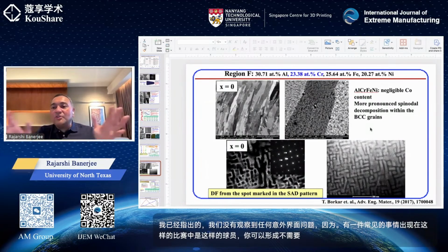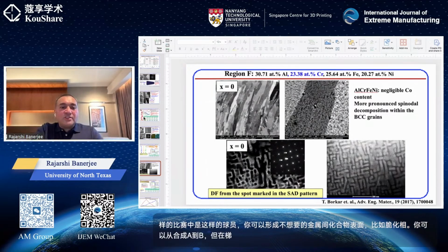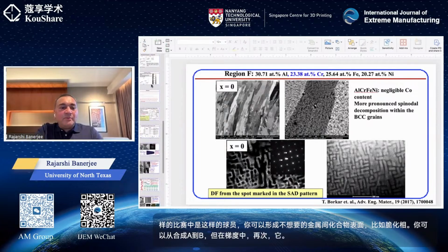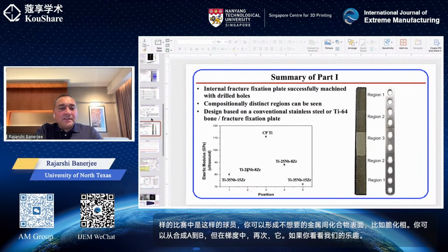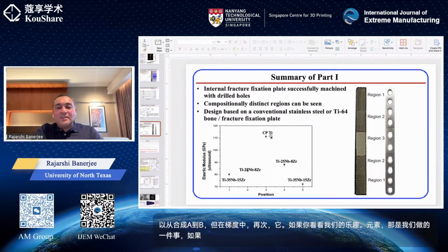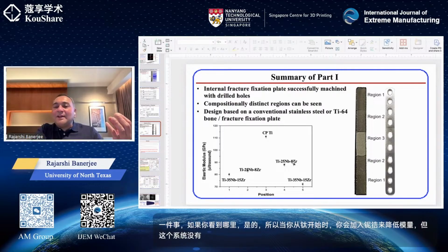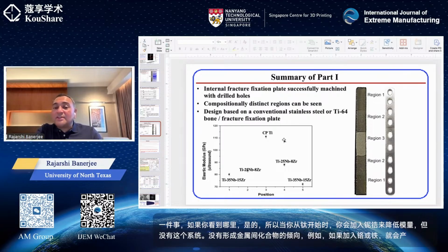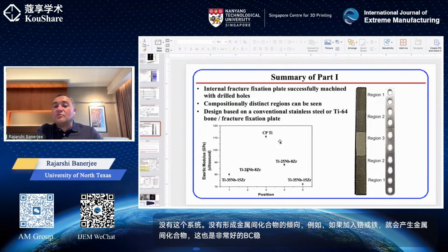You may go from composition A to B, but in the gradient, again, if you look at the choice of our elements, that's one thing we did. If you go from titanium, you're adding niobium and zirconium to reduce the modulus, but none of this system has a tendency to form an intermetallic compound that can be embrittling. If, for example, I had added chromium or iron, which are also very good BCC stabilizers and can reduce the modulus, I would definitely encounter